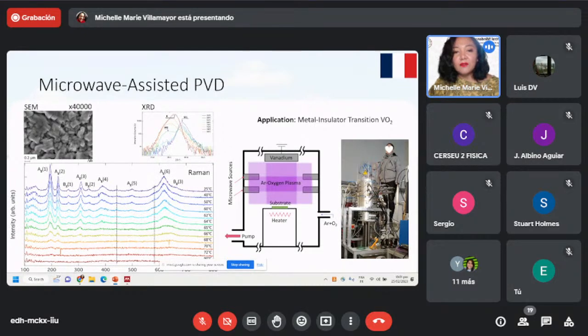We also checked for its XRD peak, and this particular position right here indicates that we have a transitioning material. So we have a VO2 R phase, M1 phase, and M2 phase, where the M2 phase is the transitioning, it's in between the R and the M1 phase.